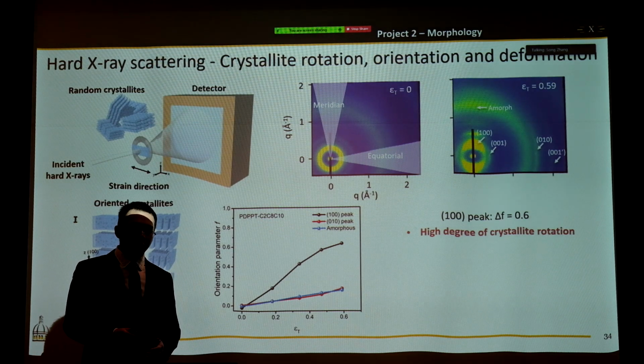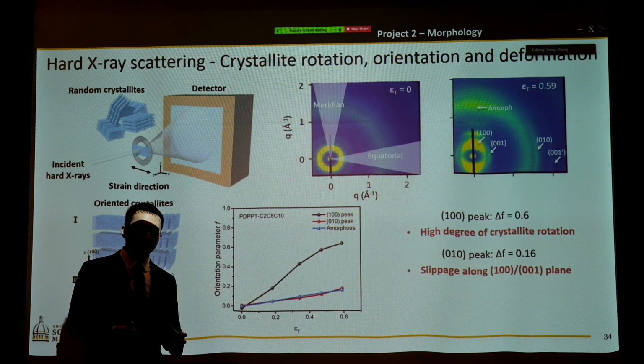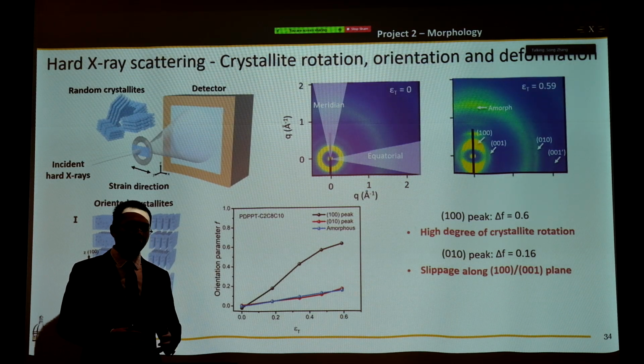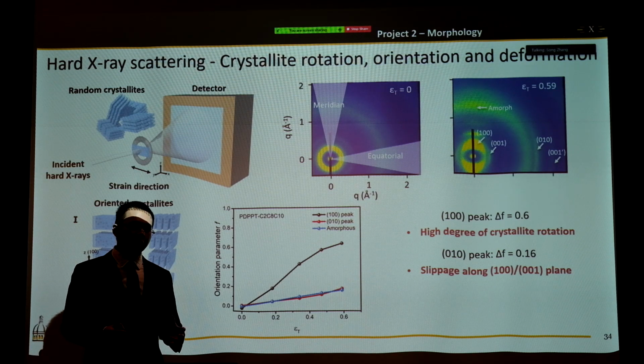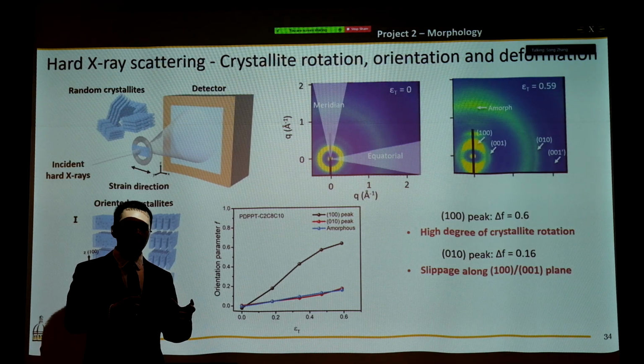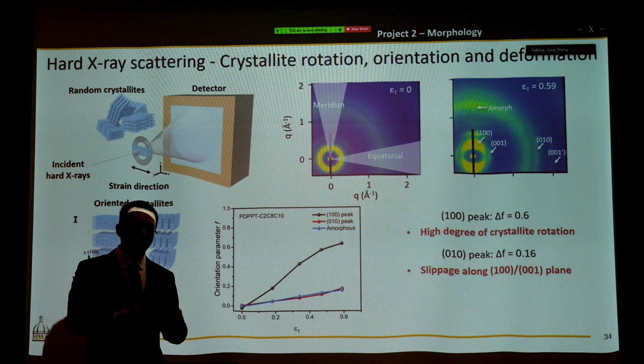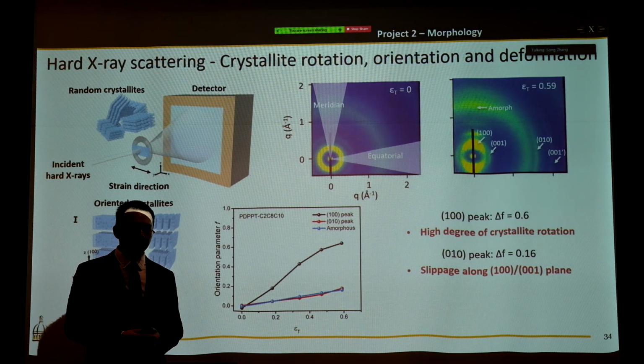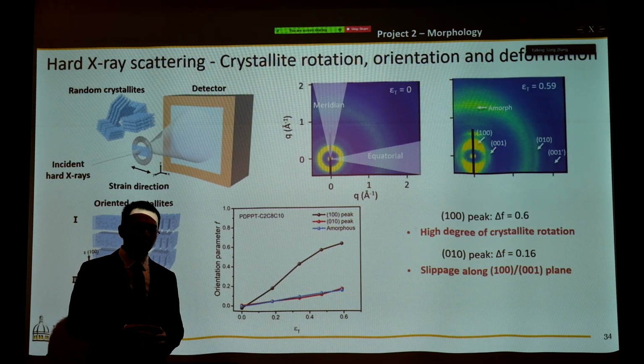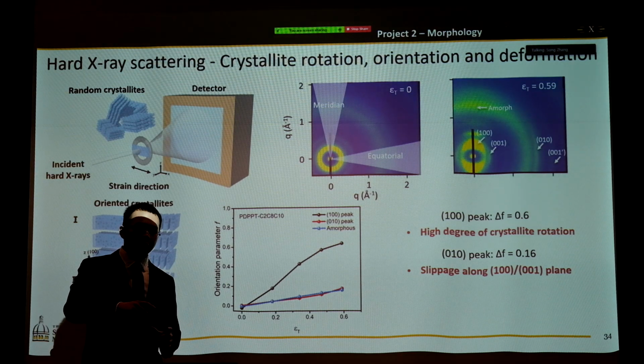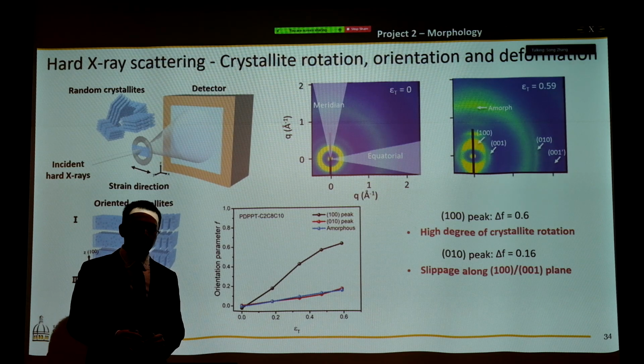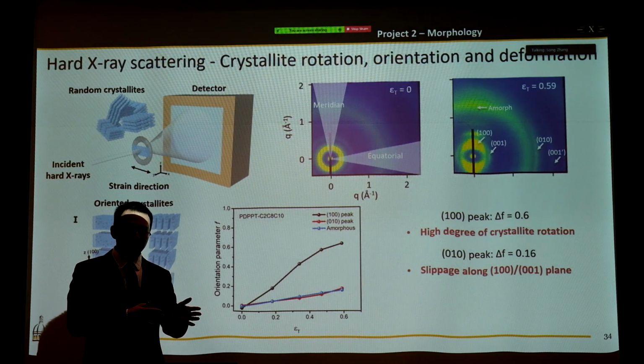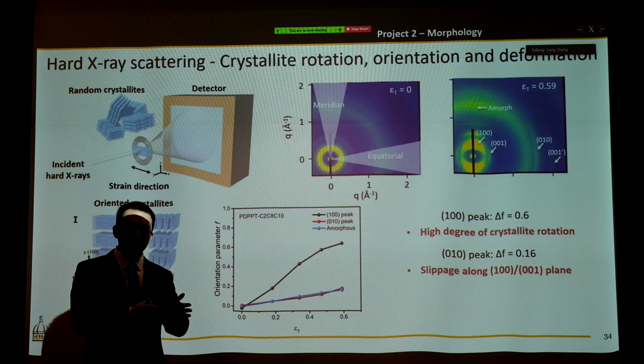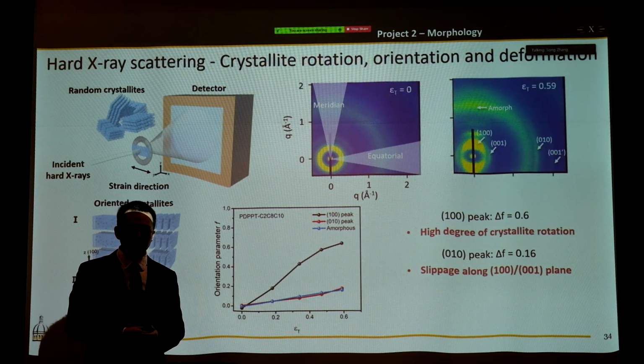However, the 010 peak does not seem to be aligned to a similar degree as the 100 peak. And why is that? It seems strange, because if a crystal does not change its shape before and after alignment, then along the 3 directions, it should show a very similar degree of alignment. But now, the delta F value is only 1/3 of the 100 peak. And we hypothesize that it's because during the crystalline orientation, there is backbone slippage in the pi-pi interaction. Since the pi-pi interaction between backbones is pretty weak, the backbone can be extracted out of the crystalline domain. That's our hypothesis, and we will prove it later.